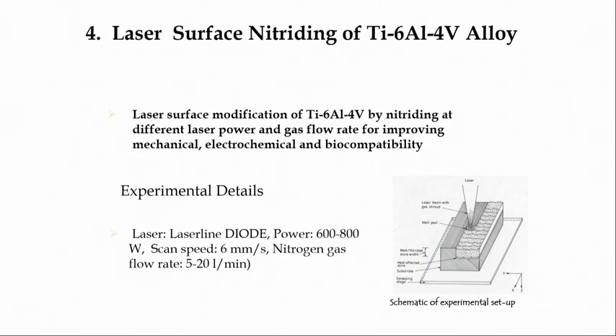Now, another way by which you can also convert the surface of metallic materials to its nitride or oxide is by melting and subsequent application of the reactive shroud. For example, surface nitriding is one such example, where there are a lot of examples on the titanium as well as steel substrate, where you can melt the surface using the high power laser beam and then use nitrogen shroud, so that there is formation of nitride layer on the surface.